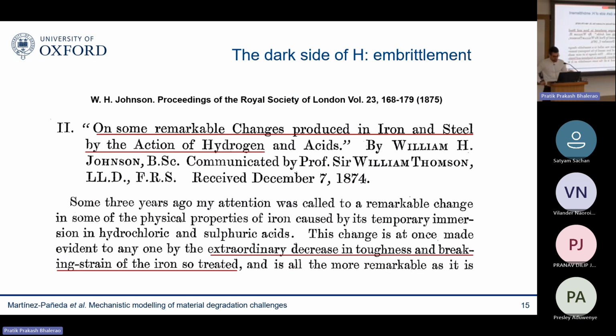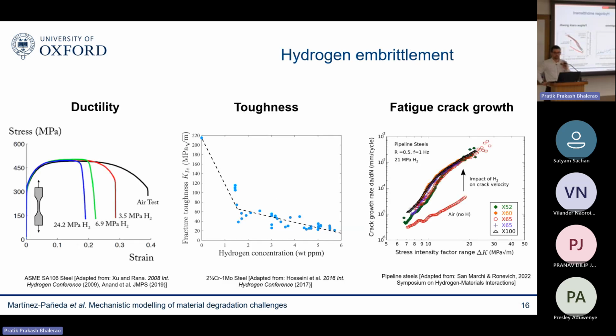And the effect of hydrogen in metals, you saw it in the previous talk, is really remarkable and extraordinary. Just to remind you of some of the key phenomena, this is the effect on ductility, uniaxial tension curves, and you can see how the failure strength is very significantly reduced when you expose your metals to hydrogen, in this case, hydrogen gas. The reduction in toughness is even more impressive. This is fracture toughness for a pressure vessel steel. You can see that 6 parts per million of hydrogen, so a tiny amount of hydrogen, can bring your fracture toughness from above 220 megapascals per meter to below 20 megapascals per meter. So an order of magnitude drop with a tiny amount of hydrogen.